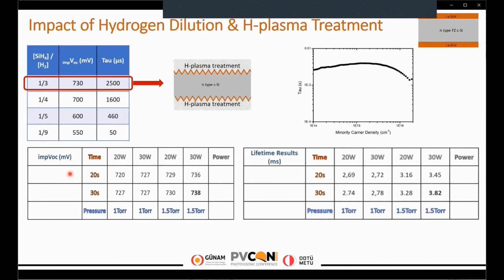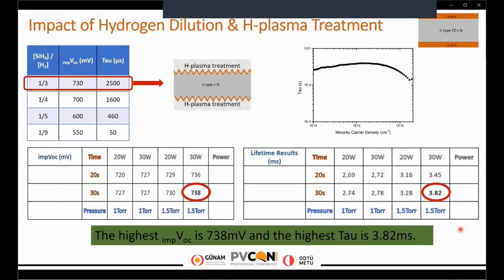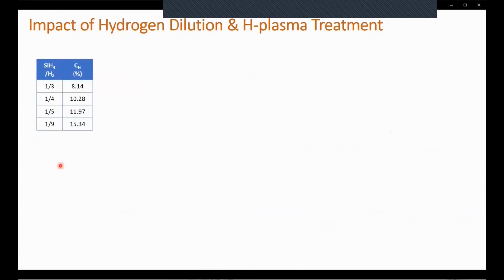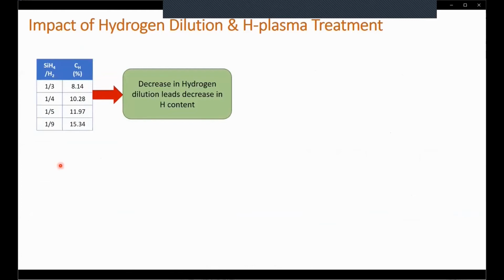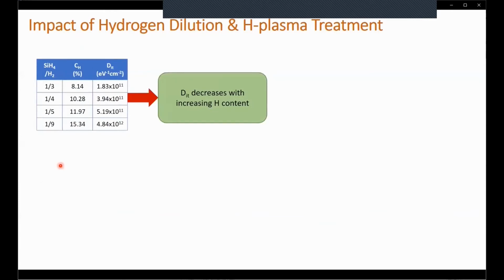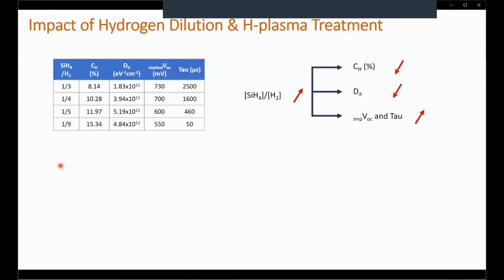On the left-hand side, you can see the implied VOC variation, and on the right-hand side, you can see the lifetime results. At the end of the optimization set, we have achieved the highest implied VOC of 738 millivolts, and the highest effective lifetime is 3.8 milliseconds. When we look at the impact of the hydrogen dilution on the hydrogen content, a decrease in the hydrogen dilution leads to a decrease in hydrogen content. And when we look at the changes in interface trap densities, interface trap densities decrease with increasing hydrogen content. Looking at the overall results, when the silane ratio increased, hydrogen content decreases, interface trap densities decrease, and effective lifetime increases.